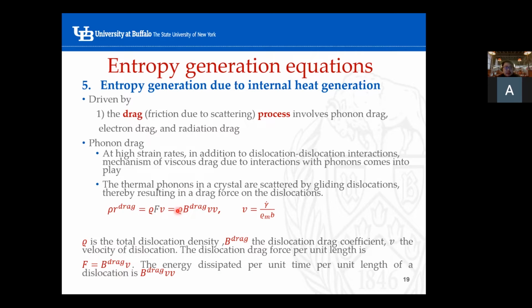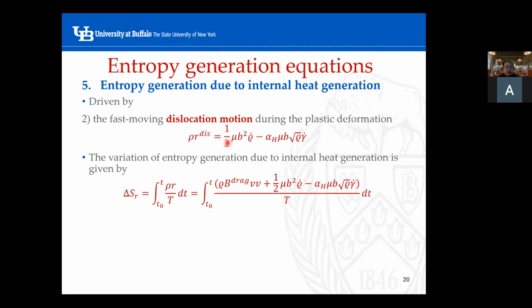So the total density of the dislocation times the force per unit length gives us a total force, and force times the velocity gives us the work per unit time. One thing I have to emphasize here is that the dislocation density is closely related to the shear strain rate. So this term is actually strain rate dependent, and strain rate will affect the contribution of this equation. So this drag mechanism term is strain rate dependent.